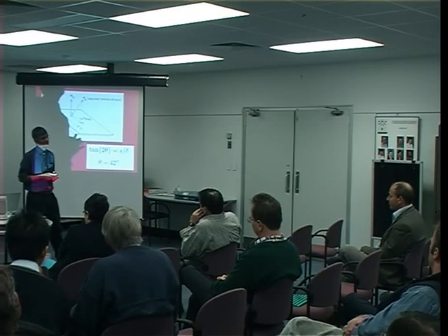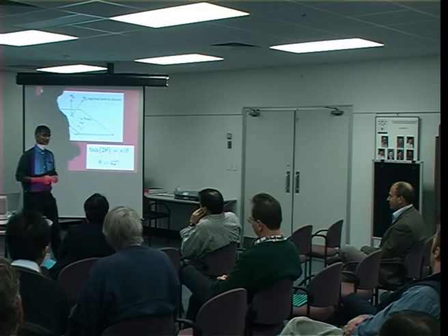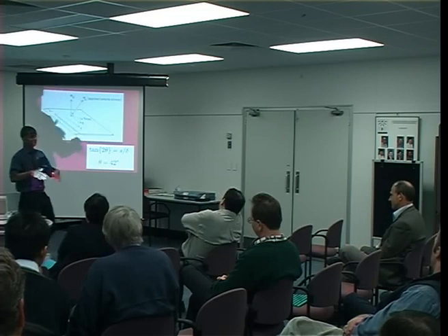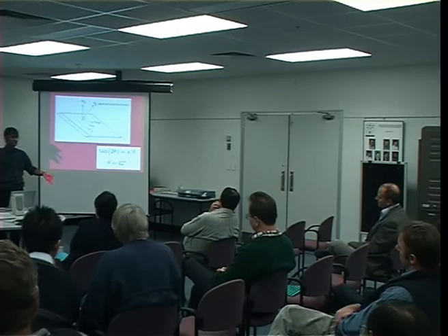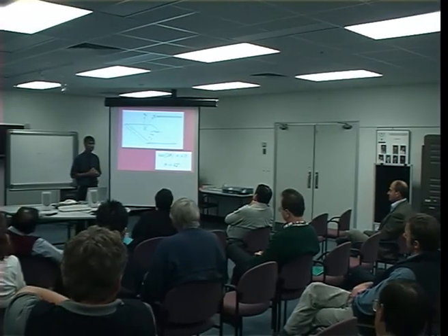So what would the microstructure be? A ferrite supersaturated with carbon, exactly right. Carbon is really unhappy there. So it would not be very stable. If you temper it, it precipitates or goes into the austenite. So it's not a stable microstructure.